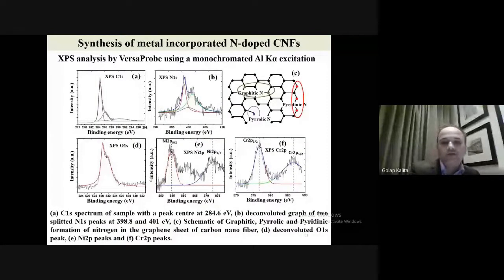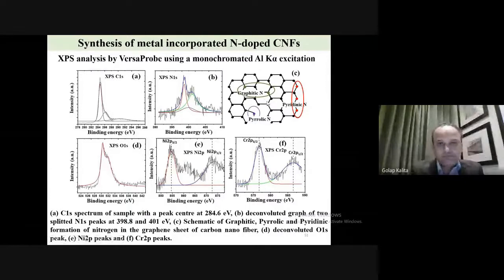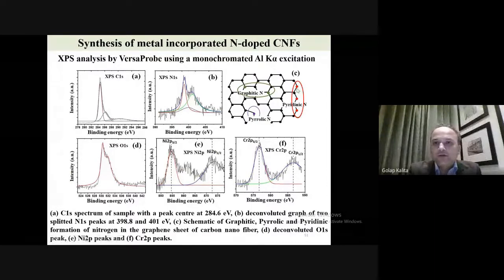So you can have nickel and chromium incorporation, then we have nitrogen incorporation in the fibers. If you see graphene, nitrogen can be incorporated in different forms. If a nitrogen atom replaces one of the carbon atoms in this type of ring, it is called graphitic nitrogen. This nitrogen is connected to 3 different carbon atoms, so it is graphitic.